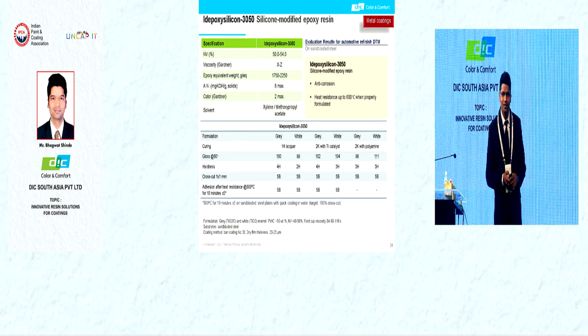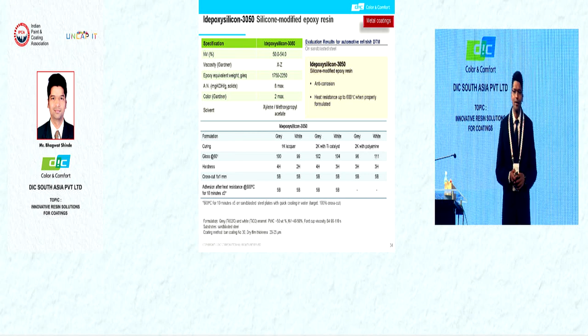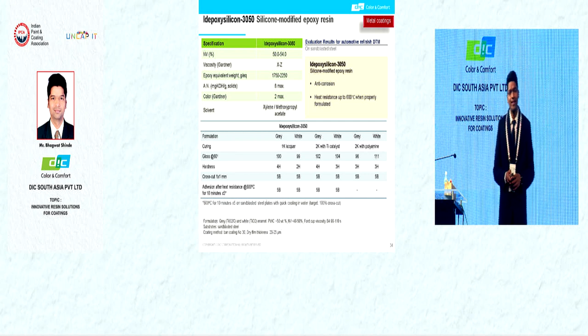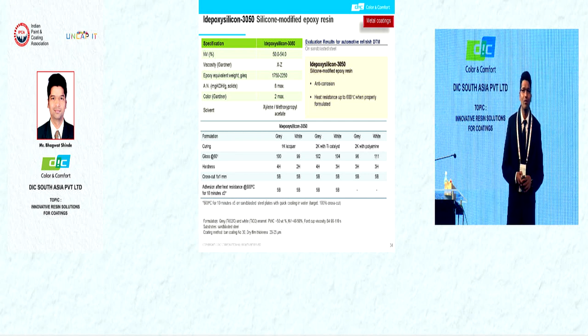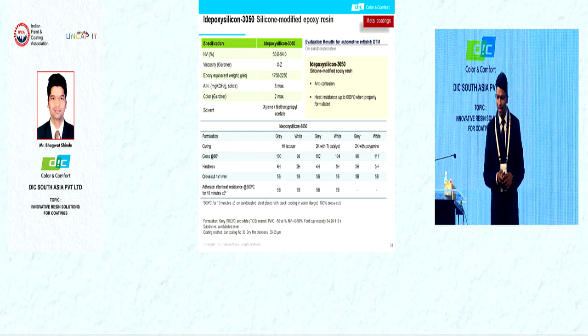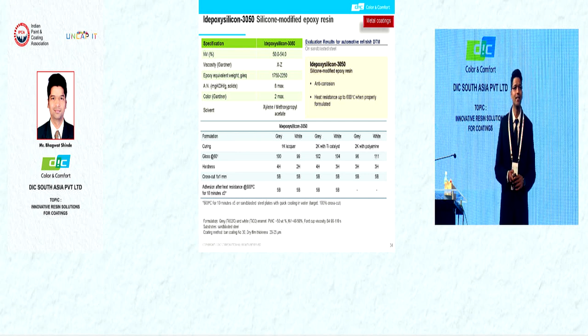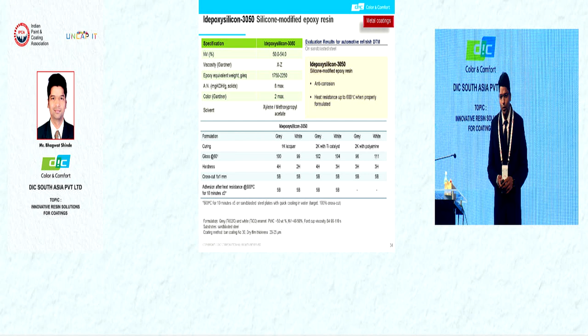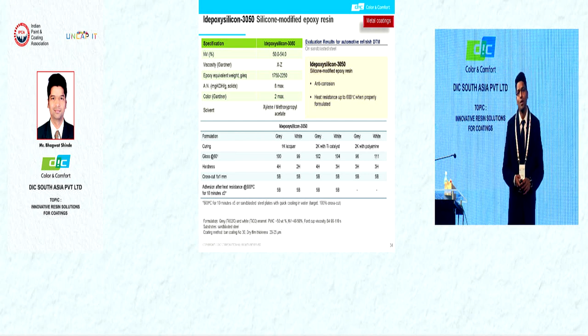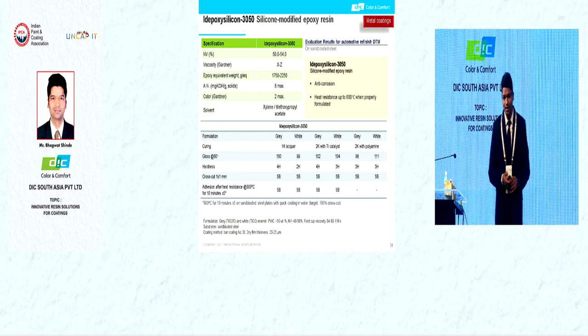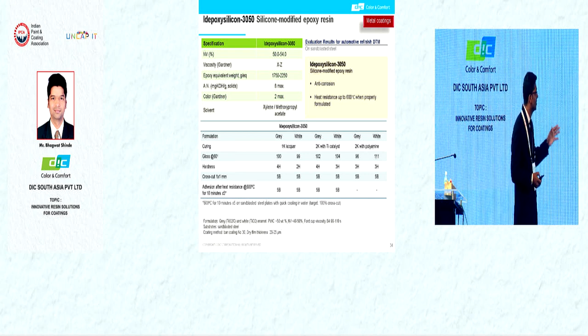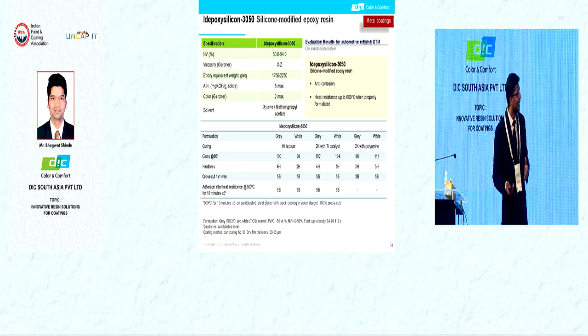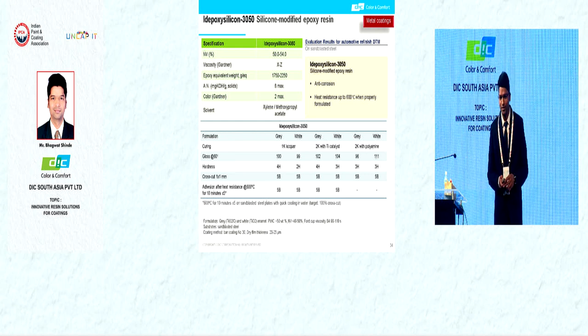The next specialized product I would like to introduce is for the heat resistance coating, Idepoxysilicon-3050. This is a silicon modified epoxy resin. If there is a requirement of heat resistance up to 600 degrees, we recommend this product for that particular application, and mostly this product is used for motorcycle silencer coatings. You can see here, this product also shows good anti-corrosive properties with heat resistance. And in the table, you can see, you can use this product as a 1K lacquer or 2K with titanate catalyst and 2K with polyamine. So this product we recommend for heat resistance coatings.